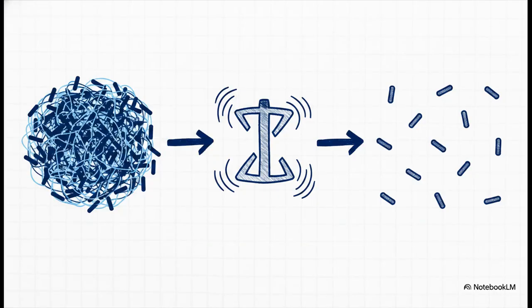Of course, working with materials down at this tiny scale presents some surprising engineering hurdles. You really have to watch out for agglomeration. Those nanoscale cellulose nanocrystals naturally want to hydrogen bond with each other. If they clump together, they completely lose their reinforcement power. To fix this, the processing protocol demands advanced surface TEMPO oxidation, or using a high-shear mixer to make absolutely sure those nanocrystals don't clump and stay perfectly dispersed throughout the matrix.